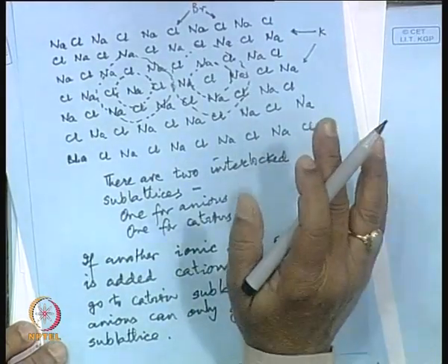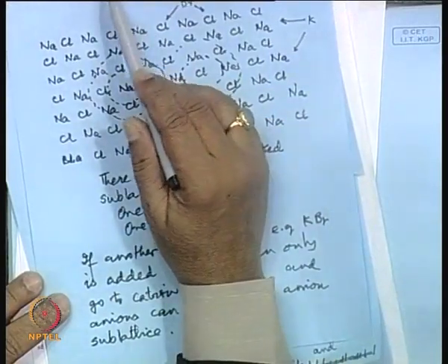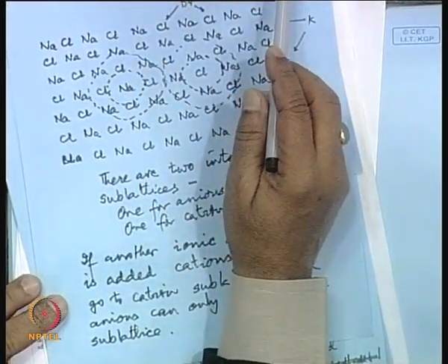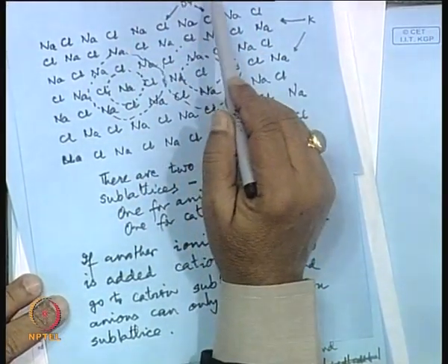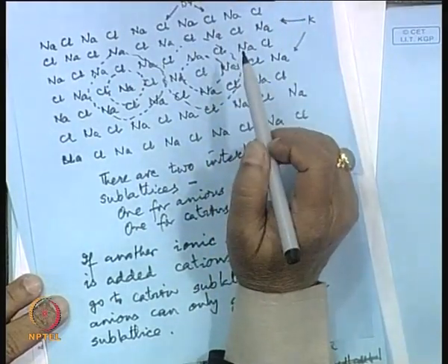So, we can say that in the liquid state, there will be no solid order which goes into infinity, but there is short range order, that when the solid transforms into molten state, this order prevails in short distances. And in the short distances, we will have sodium ions surrounded by chloride ions surrounded by sodium ions. This is required for the sake of electroneutrality.